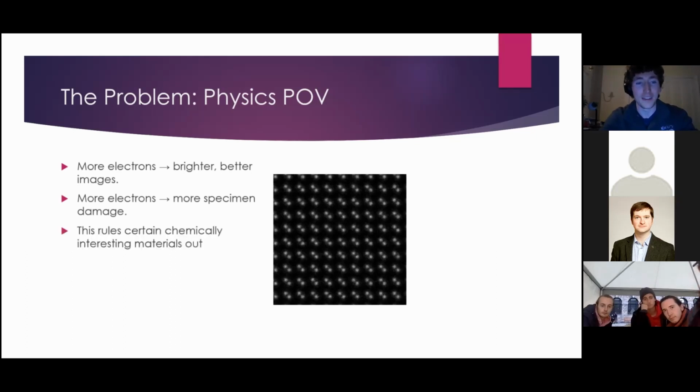So if you can somehow put these specimens in a lower intensity environment and still retain decent image quality, it really widens the range of materials you can characterize. But if you use fewer electrons, you absolutely incur image noise, and there's no getting around that. It's just an intrinsic nature of the amount of signal that you're using. And this noise can be pretty damning. It has this weird feedback loop that develops when you're at the microscope trying to squeeze out the best image possible,